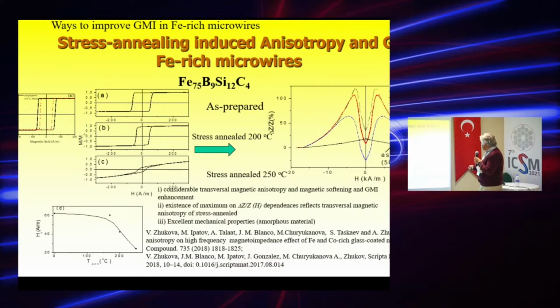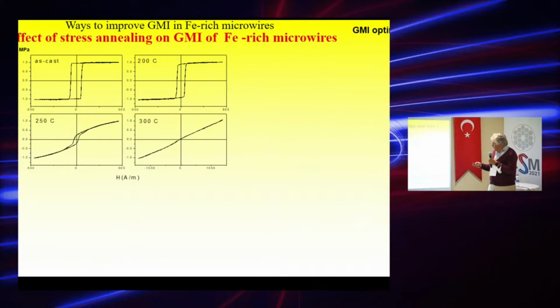And then once we measure the magnetic impedance effect, this is the dependence of magnetic impedance ratio on magnetic field, we observe this huge growth of the magnetic impedance effect. So recently we studied the effect of such treatment in more detail. And what we found is that there are different features.